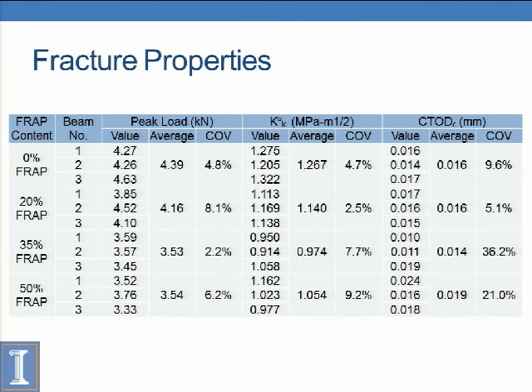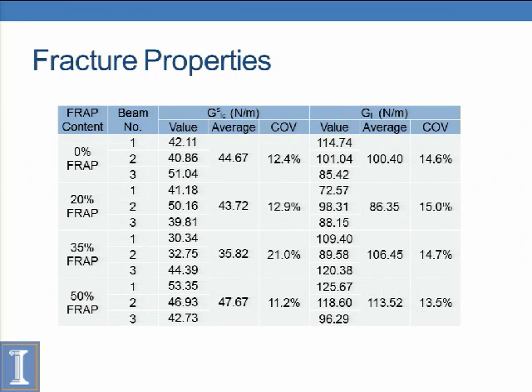So with these fracture properties, we found a decrease in the peak load, which was expected based on our strength results. So a reduction in peak load with increasing FRAP. Also a slight decrease in the fracture toughness, K1C, with increasing FRAP. The critical crack tip opening displacement was relatively unaffected here, it looks like. And then looking at our initial fracture energy, it was relatively unaffected by our FRAP content.